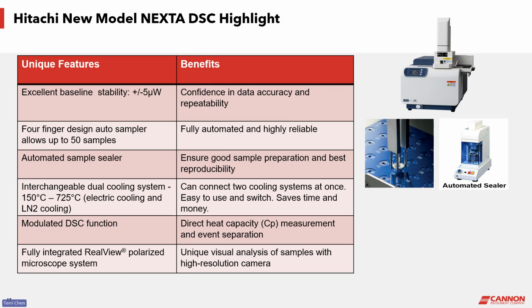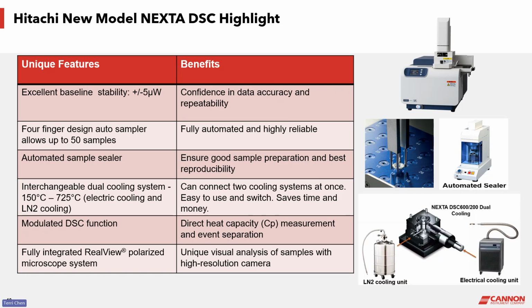One of the best technical highlights on Hitachi DSC is its flexible and interchangeable dual cooling system. Most DSC users know that a typical electrical cooling system on a DSC can cool the samples down from -40 to -90 degrees C, depending on which model you use. But if a user occasionally needs to cool the sample down to liquid nitrogen temperature, which is -150 degrees C, he or she may have to end up purchasing an additional second DSC in order to do so, which could cost more money and also take up more lab bench space. Hitachi DSC allows both the LN2 and electrical cooling system to be installed on the same DSC unit. Users can select their desired cooling system through a simple switch in the software.